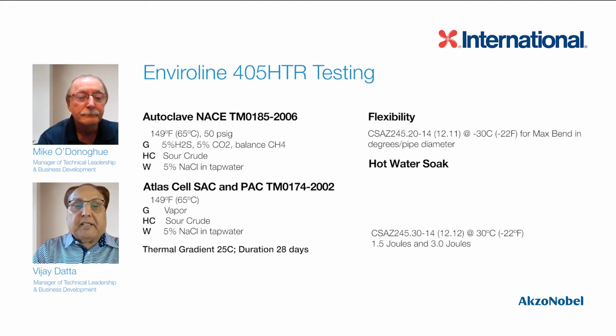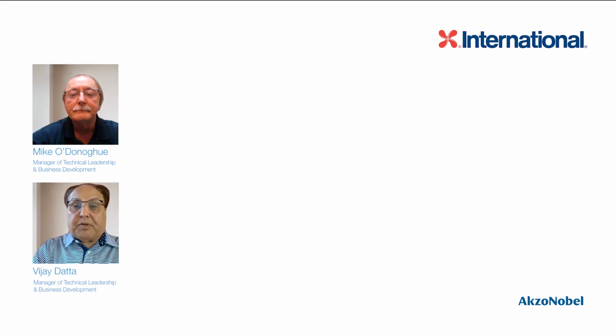And then the hydrocarbon phase is the sour crude, along with the water phase, which is 5% sodium chloride. We also run Atlas cell, both standard Atlas cell as well as pressurized Atlas cell in 3 phases. Flexibility, hot water soak, because that's required if you want to conform your coating to the pipelines, and impact test, which is really important here.